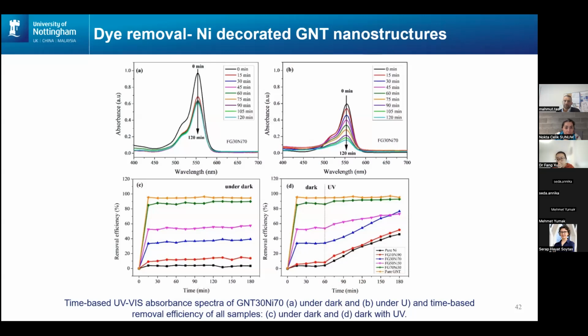The first application we tried is using those nanostructures to remove dye. We mixed them in water first and then added the dye — we used rhodamine B here. After 120 minutes it has been largely reduced, but this is only in the dark. If we then transfer it to UV light, it can be further reduced. If this is 1, it was reduced under dark conditions, and with UV light applied it is further reduced to only 0.15 left, meaning very few rhodamine B molecules remain after this treatment.